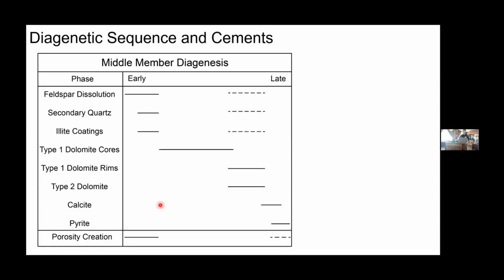But the earliest event that we observed there is feldspar dissolution. And related to that are the formation of secondary quartz overgrowths and cements, as well as illite coatings on almost all framework grains. And these three are relatively minor phases, occupying between 5 and 10% of the bulk rock volume. Following that is a series of carbonate cements that are much more prevalent, being dolomite and calcite. And we've broken dolomite into two types: type 1 cores, which were relatively early, followed by type 1 dolomite rims and type 2 dolomite. And those are all cross-cut by calcite and pyrite.